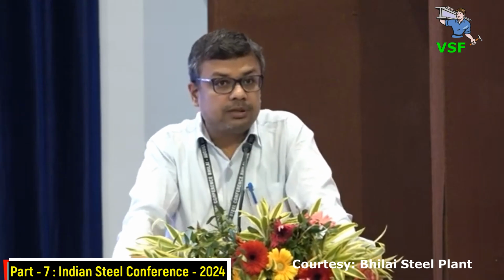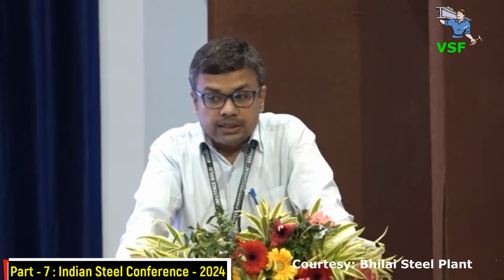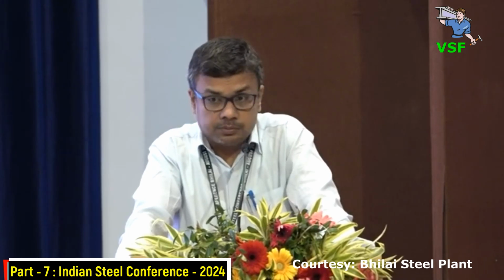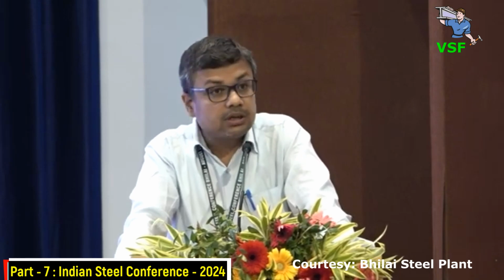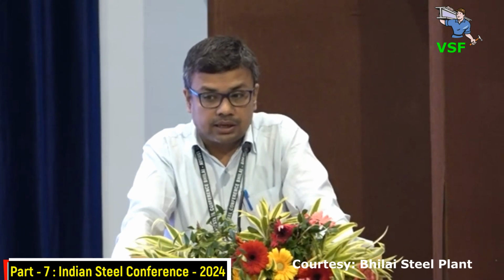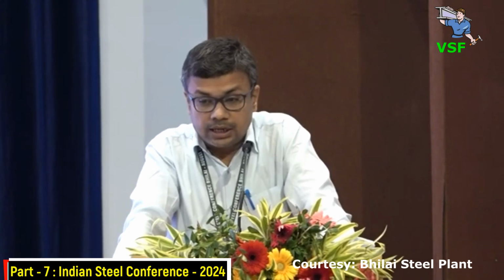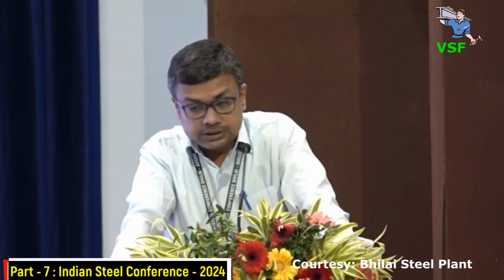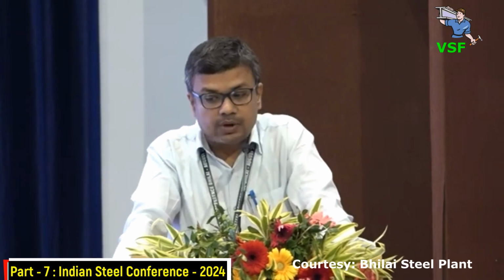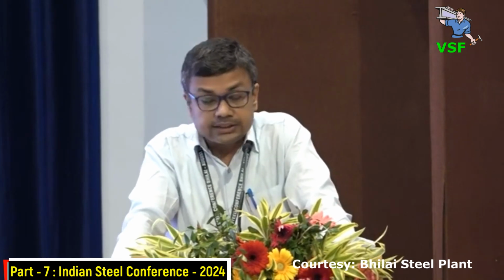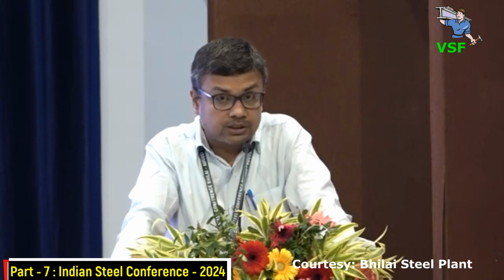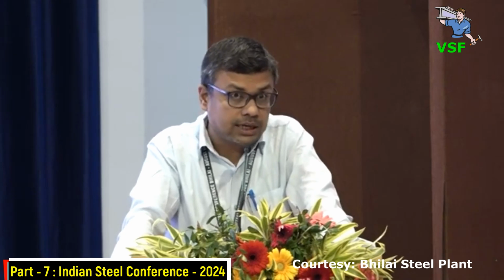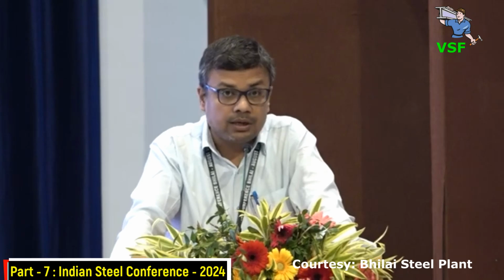Thin slab caster in place of hot strip mill. It was discussed yesterday also. In thin slab caster, our energy consumption is 0.1 Gcal per ton, whereas in conventional hot strip mill, it is 0.3 Gcal per ton. So it is already 1/3 energy consumption in the thin slab caster and direct rolling. And if you consider a 3 million ton HR coil production, meaning 9,091 ton HR coil per day, and if the coke oven gas and blast furnace gas ratio is 1:1, we can arrive at a total CO2 saving of 653 ton per day from installation of a 3 million ton thin slab caster direct rolling in place of conventional hot strip mill.